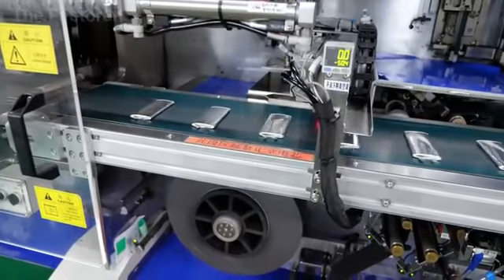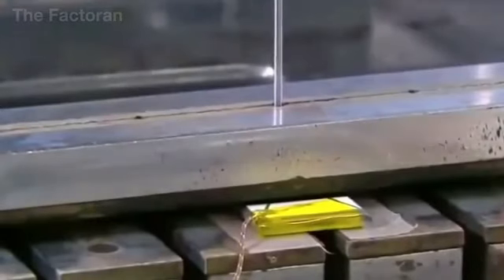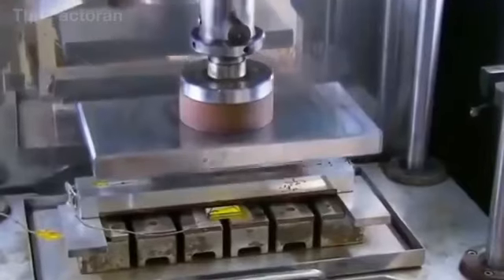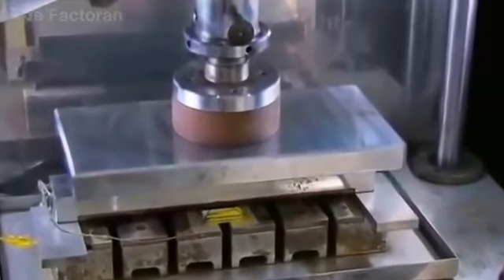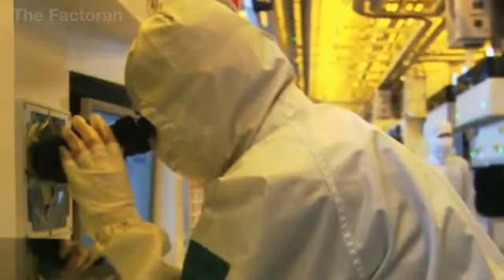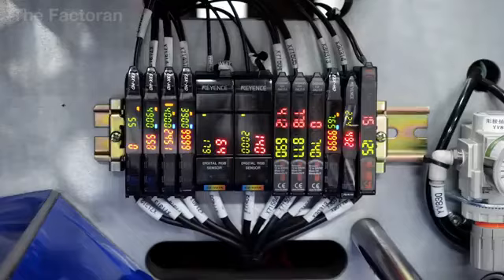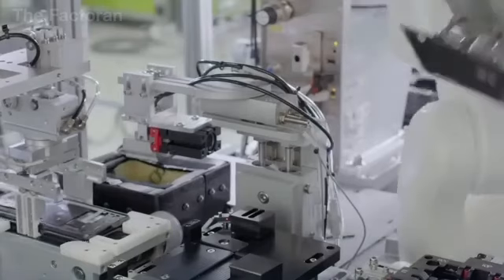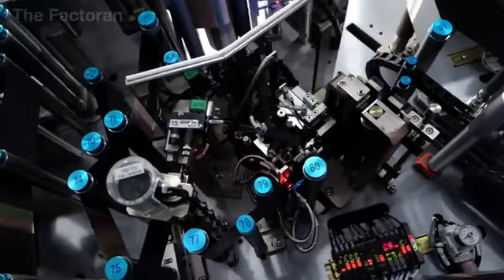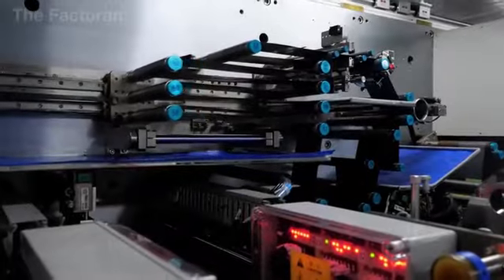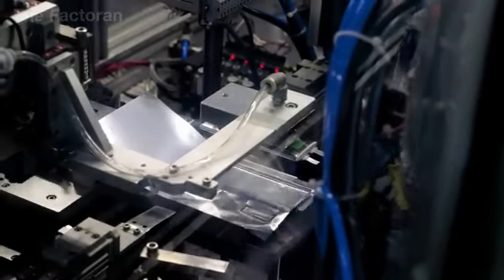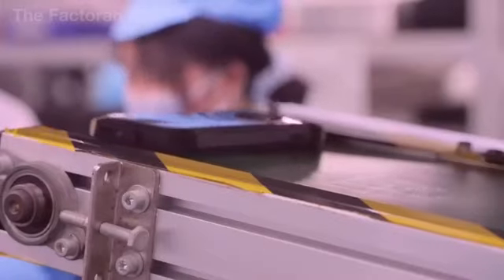Before leaving the factory, each battery undergoes a hell test. Thermal shock chambers cycle the cells between 20° and 80°, followed by dozens of continuous charge-discharge cycles to detect voltage drops, swelling, or increases in internal resistance. Only batteries that survive all these rigorous tests are labeled, packaged, and released, ensuring safe and stable operation for many years.